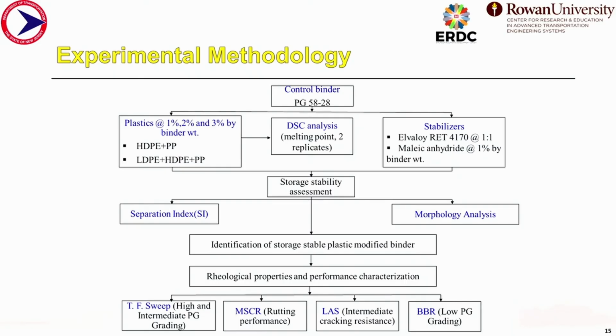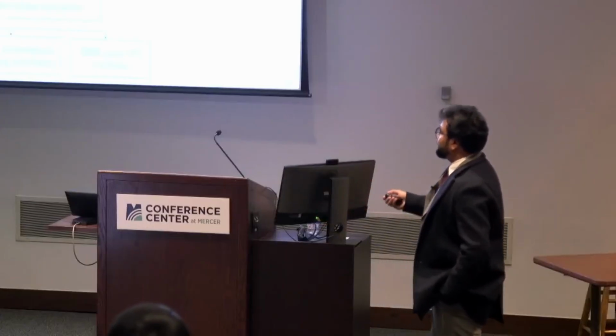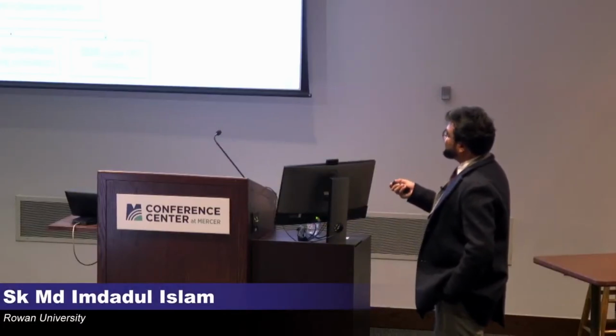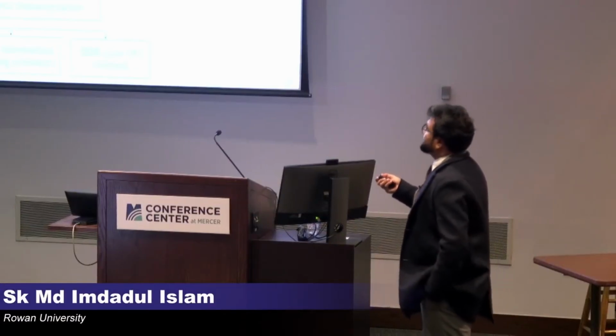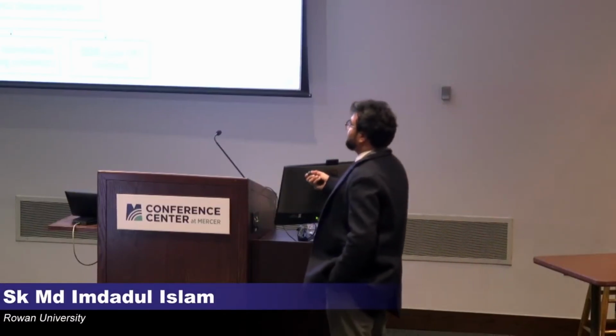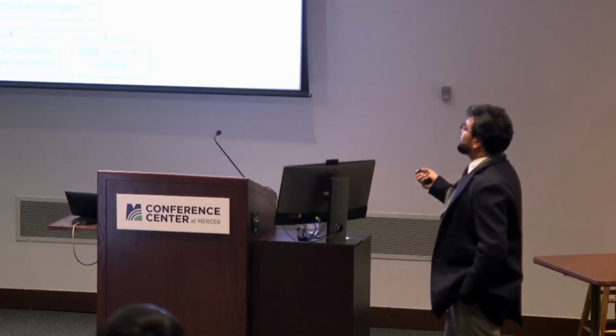As we can see, starting with the virgin binder, which is PG 58-28, considering the extreme cold weather, the whole ideology behind that was if it can be implemented in the extreme weather, then definitely it will be applicable to standard weather like New Jersey or any other weather where we don't have the extreme weather, but it will still be implemented. So the plastics, both the mixed plastics, at a rate of 1, 2, and 3% by the binder weight, and we added the stabilizers.